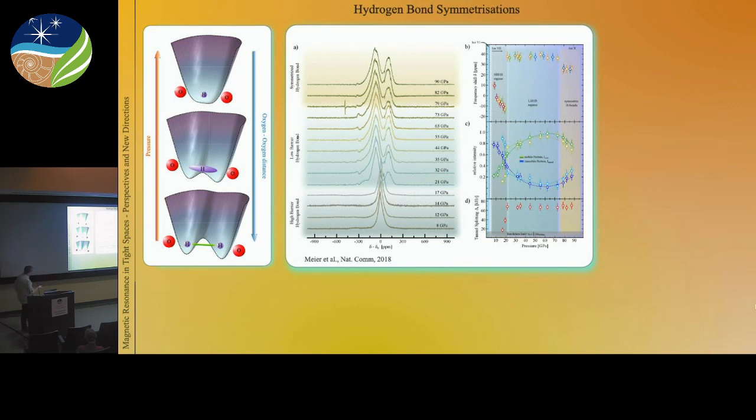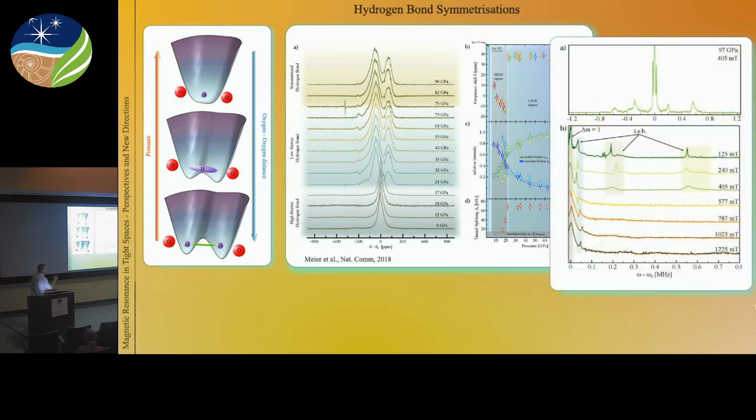And then we also went to low fields, in the range of what we would now call dipolar-driven NMR, with an electromagnet which we recently got back at this time. And here we saw that at magnetic fields of only 400 millitesla, we suddenly observe an onset of these additional signals, which are known to be tunneling sidebands, which become quite sharp at 125 millitesla.